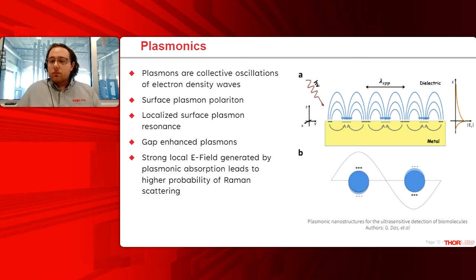Now, if a molecule that you're interested in sensing happens to fall within that field, because of that high electric field strength, you can actually get an increased probability of Raman scattering. So it's no longer 1 in a million photons. You are increasing that probability significantly. So when we talk about SERS, or Surface Enhanced Raman Spectroscopy, it's really these metal features that are the surface enhancement aspect of SERS.